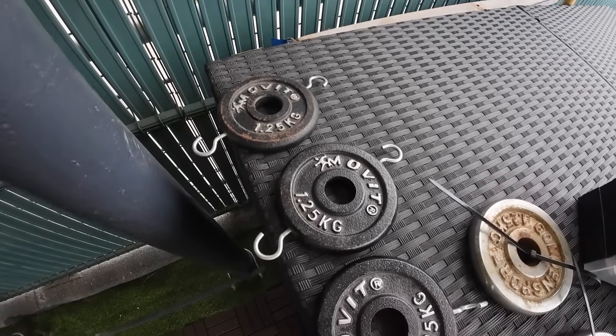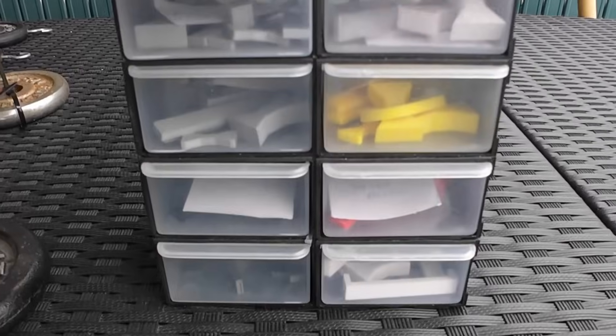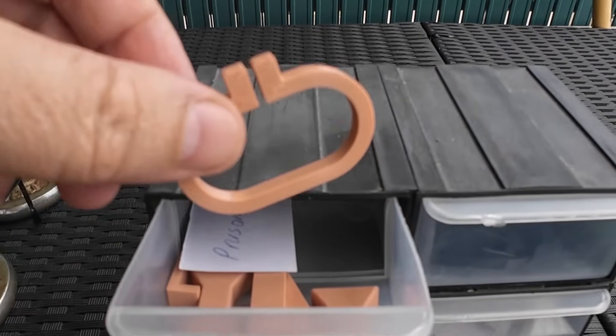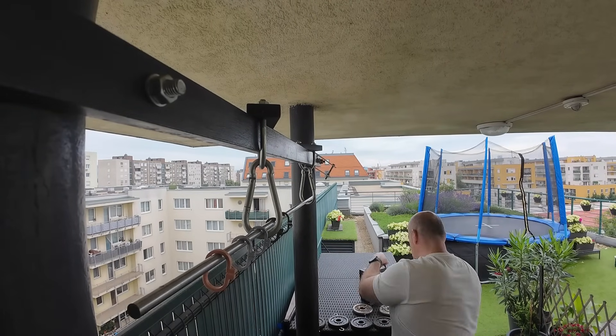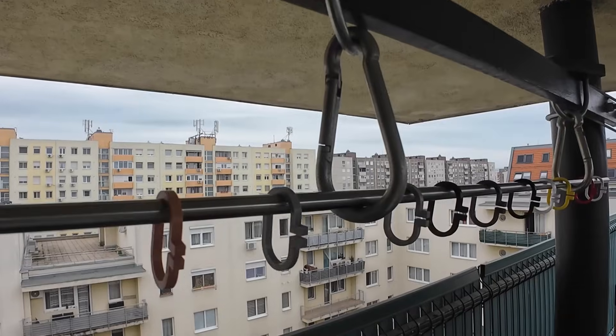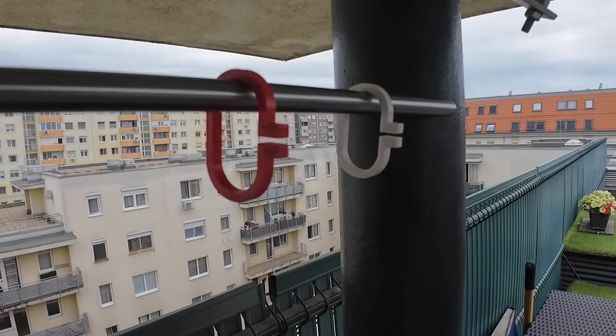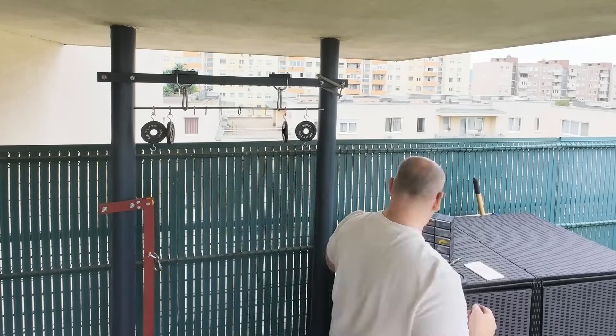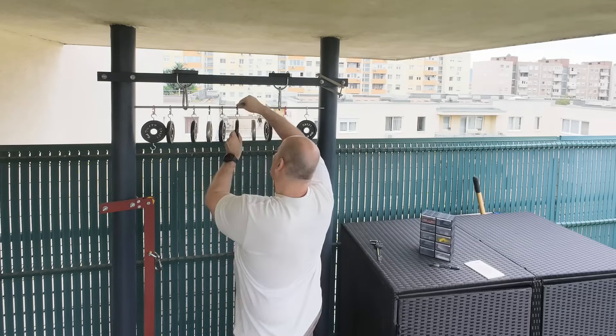For the creep test, I'm using 1.25 kg loads. The C-shaped test objects — which you may have seen in my earlier videos — are placed on a shaft outside for seven days. I'm measuring the distance between two reference surfaces, which is 12 mm without load, then immediately locking the position after placing the loads.